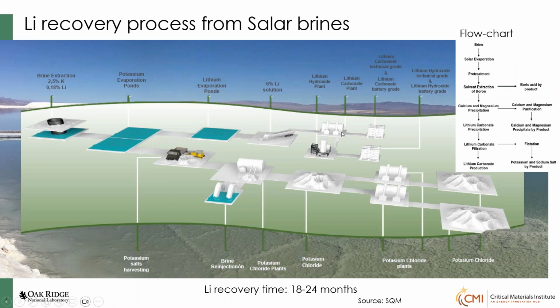So this is the flow chart for the Salar brines, conventional brines. Here the lithium recovery takes 18 to 24 months. You can see different ponds. They just use solar evaporation, and it's a slow process, but still you can achieve, we saw, 40 to 50% lithium from the Salar brines. Next slide, please.